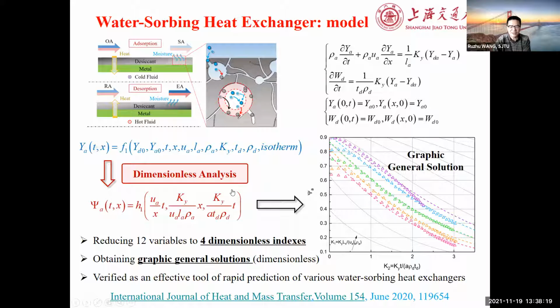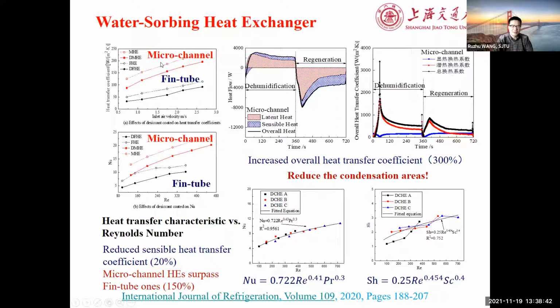We had to do a dimensionless analysis because there are too many specific data, but in the end we treated only 4 of these integrated parameters. So we are using 4 dimensionless indices and obtaining a graphic general solution. And also we made a comparison of a micro channel heat exchanger with fin-tube heat exchangers. So the micro channel heat exchanger could be much better than fin-tube heat exchangers. And also we got the analysis and measurement data for the Nusselt number and the Sherwood number for the heat transfer and also handling of latent heat for the dehumidification.